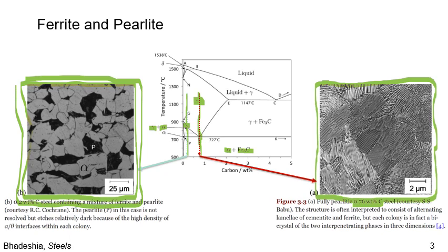So again, why is there more of the ferrite phase? Well, it's because for the low carbon content, we first hit this ferrite boundary, and so ferrite nucleates and starts to form from the austenite grains, and then we later hit the pearlite boundary. So under equilibrium conditions, the ferrite will form first, and then the pearlite will not form until after we cross under 727 degrees Celsius. So then that pearlite forms. The ferrite forms first, and then the pearlite forms from the remaining austenite.